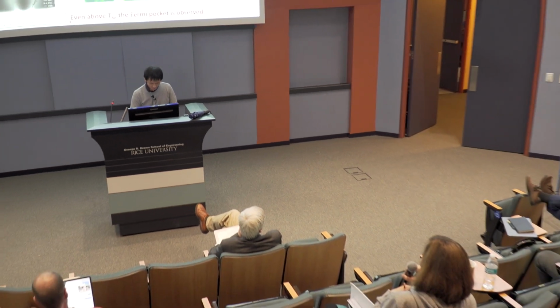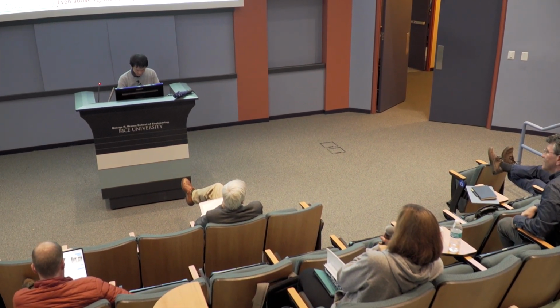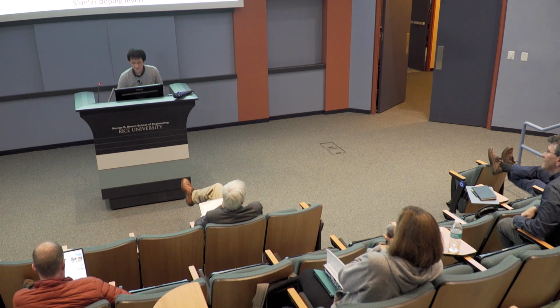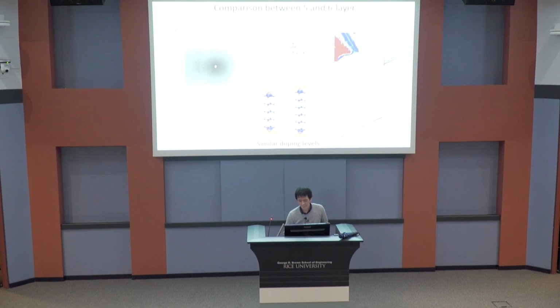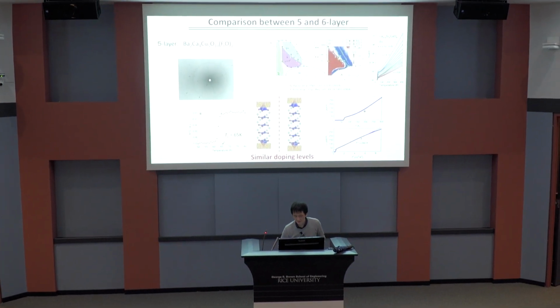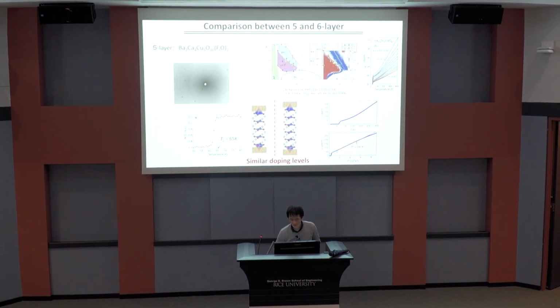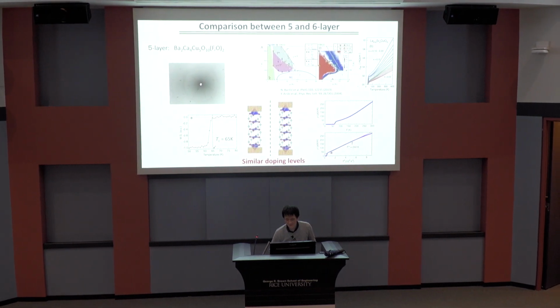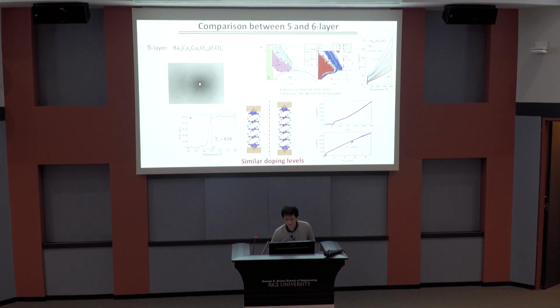So, the last question. A very simple question, what's the resistivity like? Resistivity? Did you show it? Yes. At least for the 6-layer, it must be similar to the 5-layer case, and it's kind of T-square. This is the raw data, and here I plot it as a function of T-square, and you can fit it linearly up to 240 Kelvin, which is comparable to the really heavily underdoped case for many other cuprates. Okay, thanks.